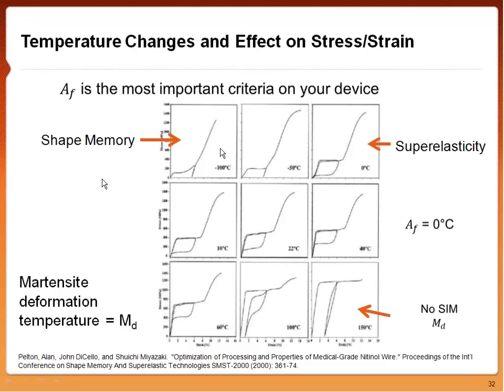When we start at negative 100 degrees Celsius, we see a typical Martensitic stress strain curve. We move to negative 50, we see the plateau raise a little bit, but we still see the typical Martensitic stress strain curve. Finally, when we reach 0 degrees Celsius, we see a superelastic curve with a flag that has the hysteresis. And again, this sample has an AF of 0 degrees Celsius.